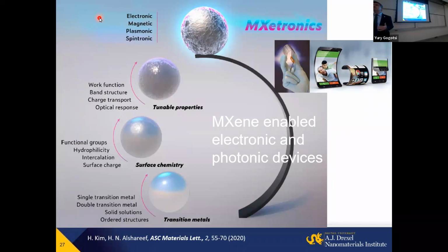In many cases, we also build hybrids. For example, we hybridize and combine MXene titanium carbide (Ti3C2) with molybdenum disulfide, or with graphene oxide, or graphene, depending on the application we use, or with carbon nanotubes to improve accessibility to the layers in electrolyte and battery electrodes. So again, it is important, and it shows how quickly the field grows.